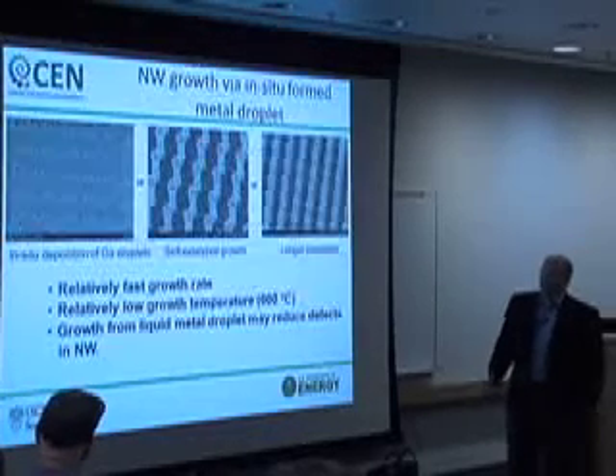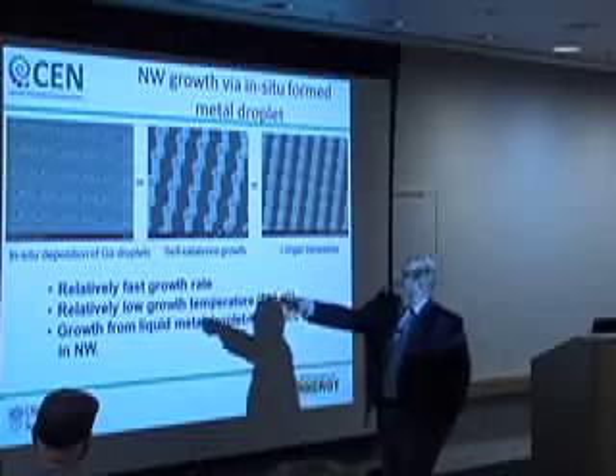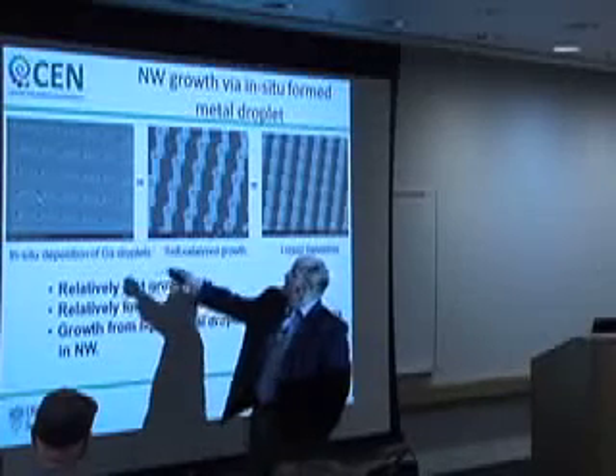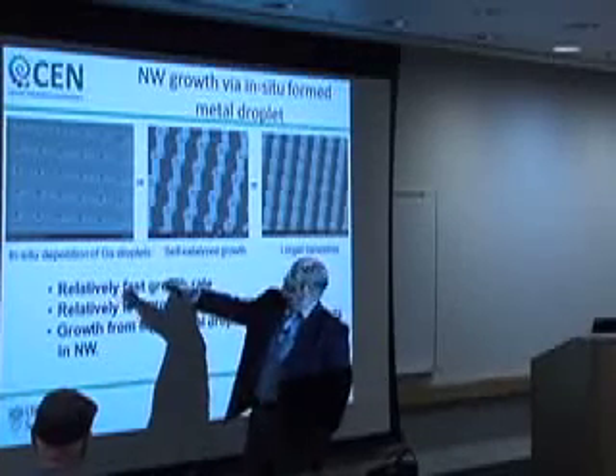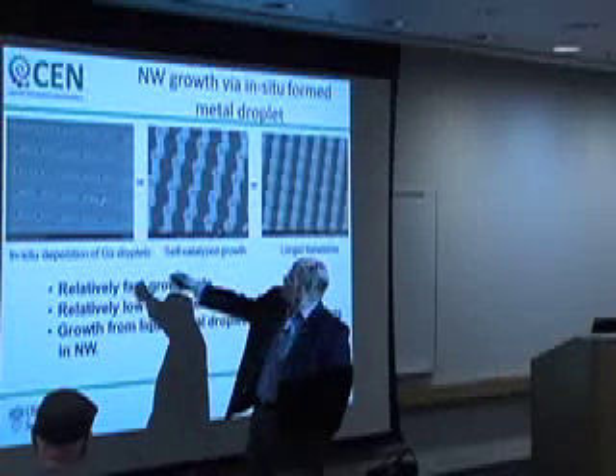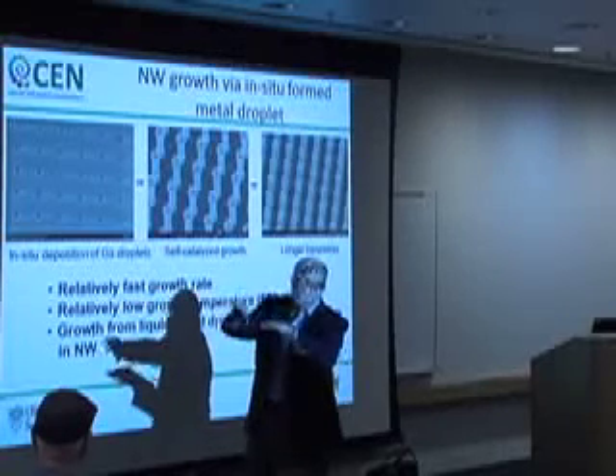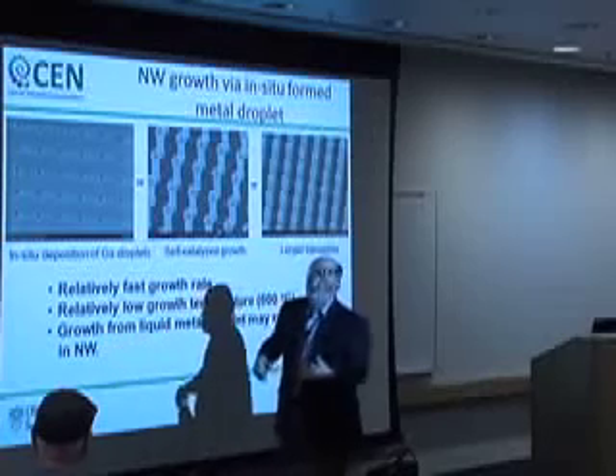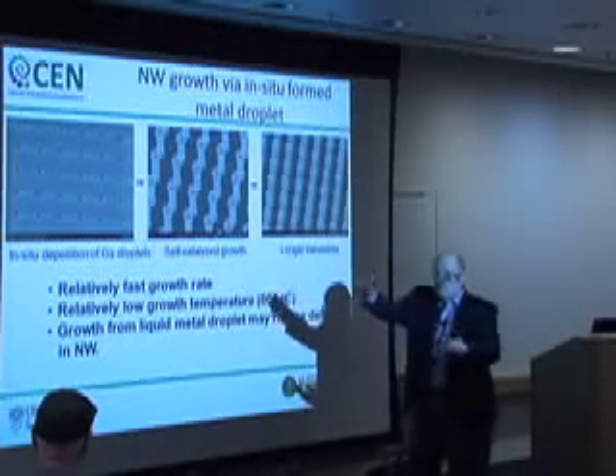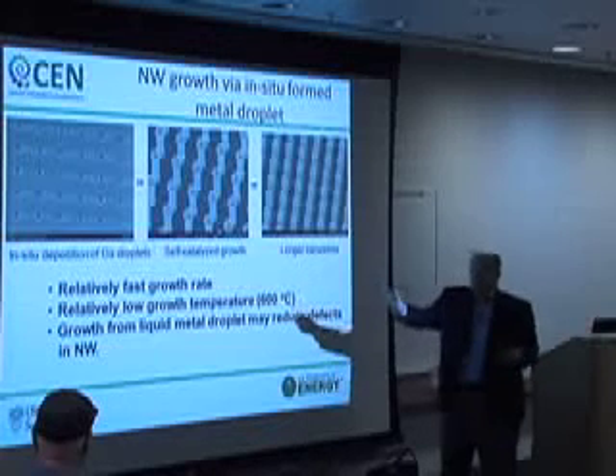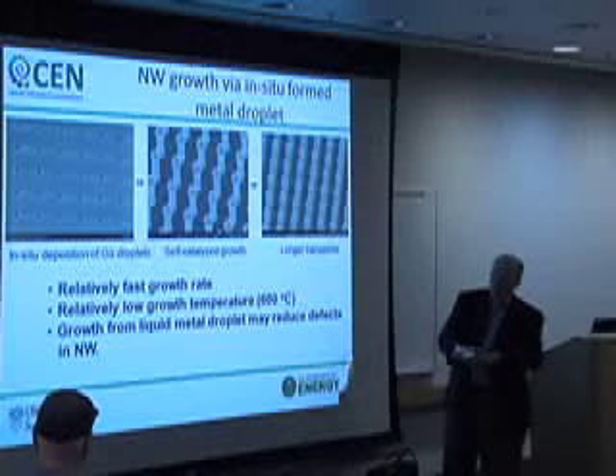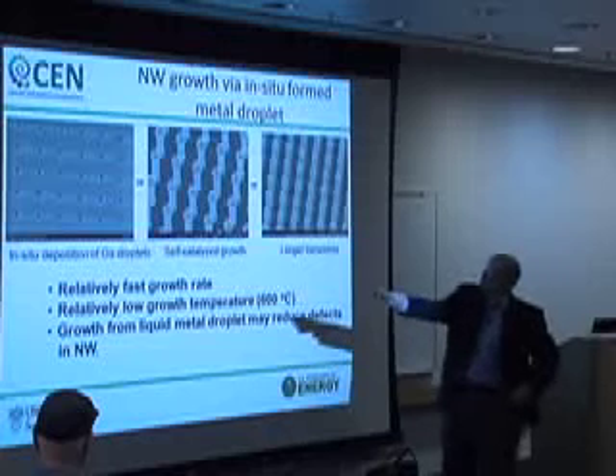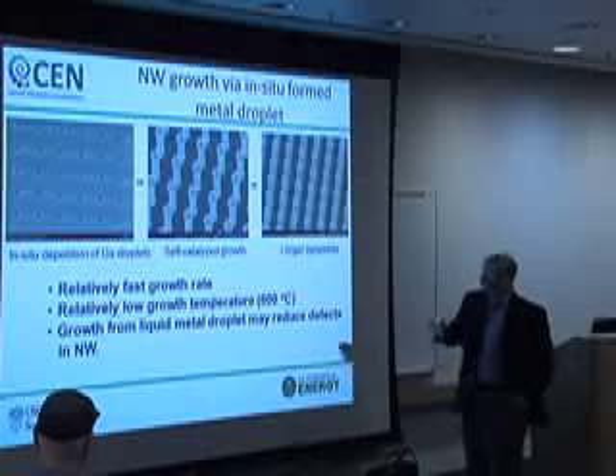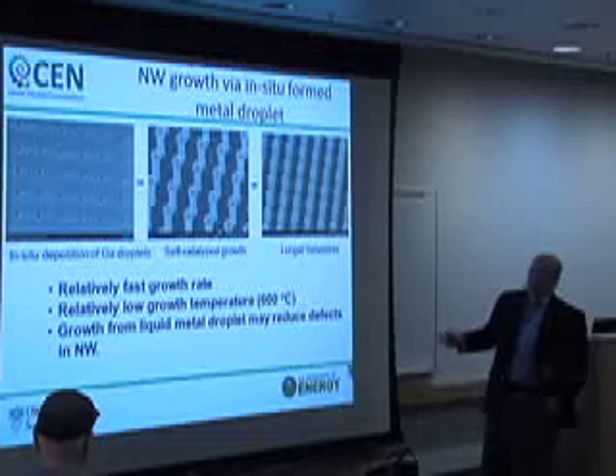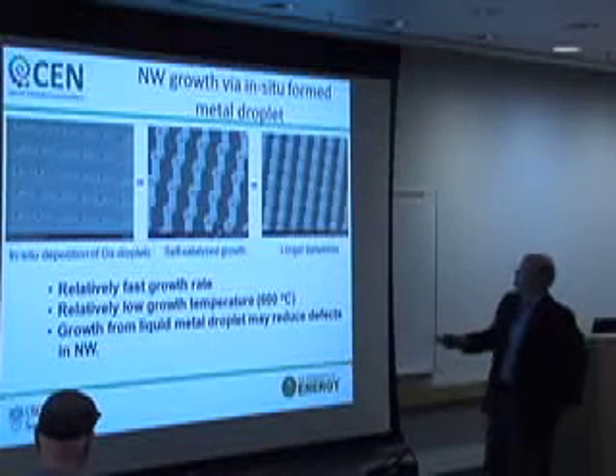Was there an SiO2 mask on that when you started? Yeah, there is. It's silicon nitride in our case, but yes, there's a mask with an opening. And what you're looking at here is the top of a hemispherical deposit of gallium. So we just turn on the gallium for a while at elevated temperatures and then pull it out of the reactor and look at it, and there are gallium balls pretty uniformly distributed in those holes. And then when we grow the nanorods under the right conditions, they will go directly out of that.